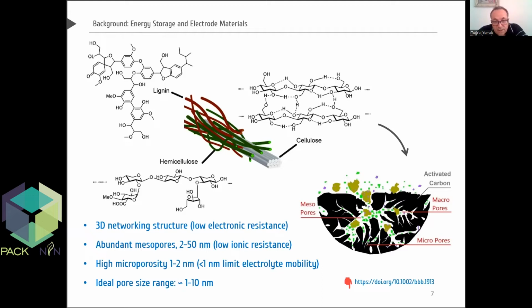Pore size less than 1 nanometer limits the electrolyte mobility, so we require the ideal pore size range of almost 1 to 10 nanometers for an ideal activated carbon electrode.